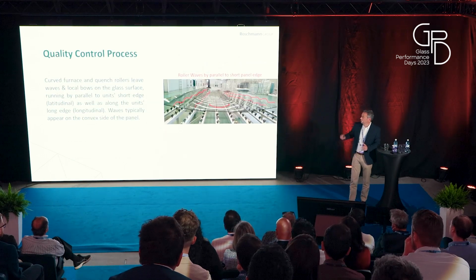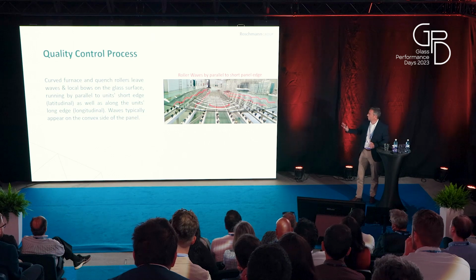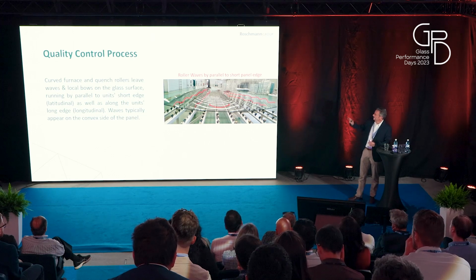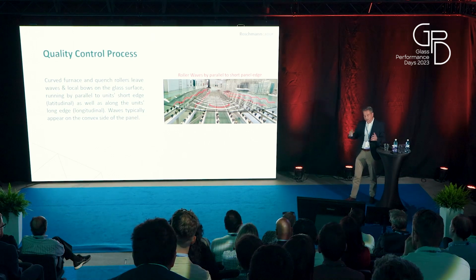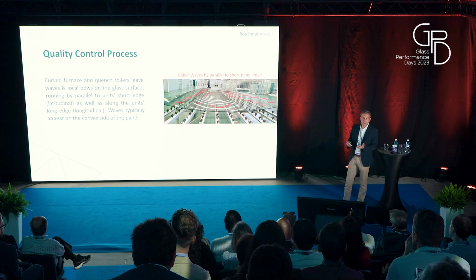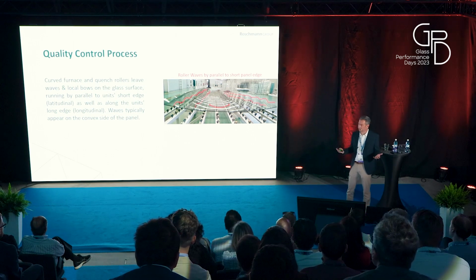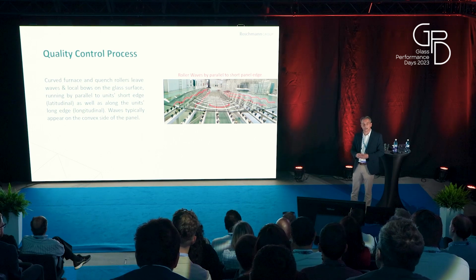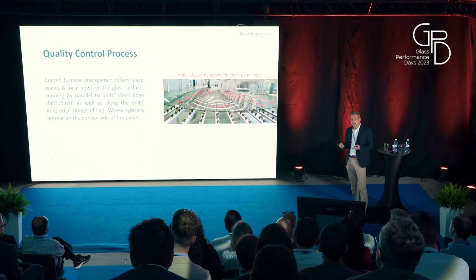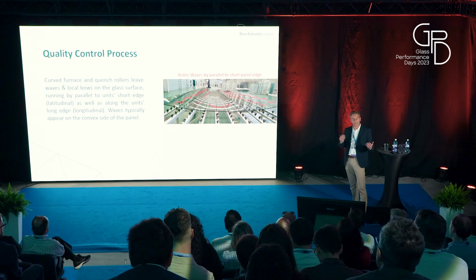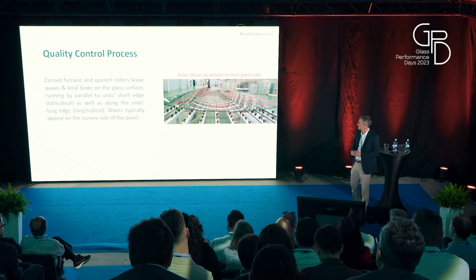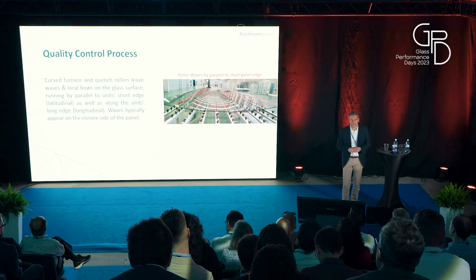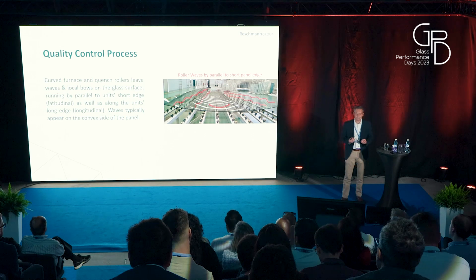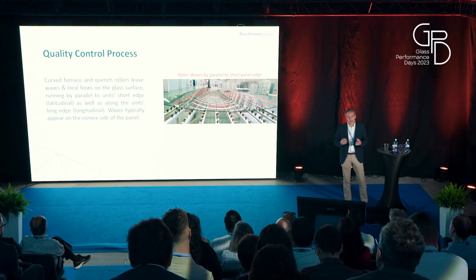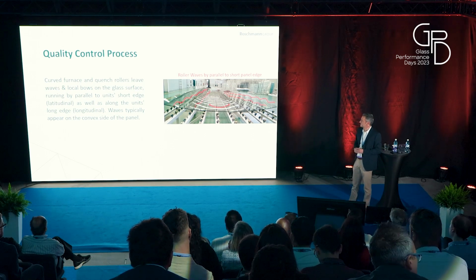So in the quality control process, I need to see what I am fabricating. This is what you see on a very typical tempered glass. It doesn't necessarily need to be a curved tempered glass. It could also be a flat tempered glass. So I do have roller waves, which can be more or less pronounced depending on the glass thickness, the temperature and the setup in the furnace, which appear on the glass surface. And usually the target is to minimize these roller waves as best as possible.